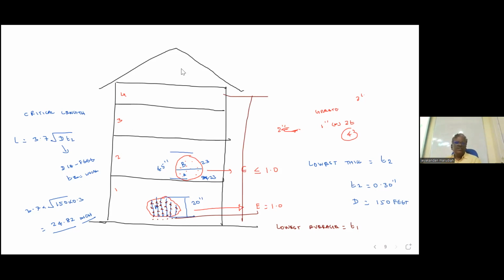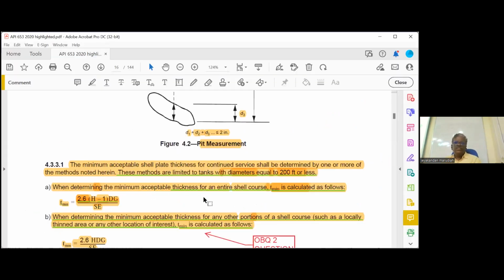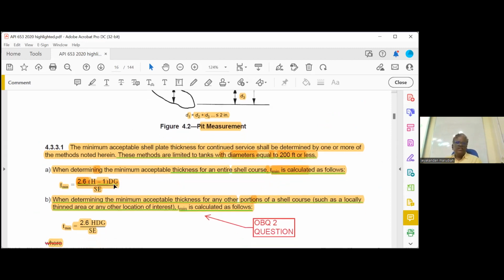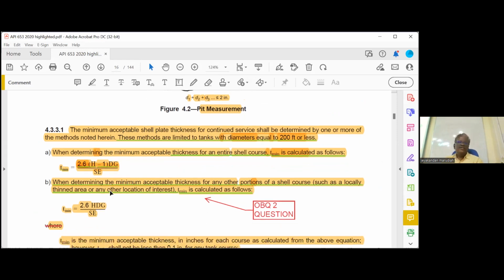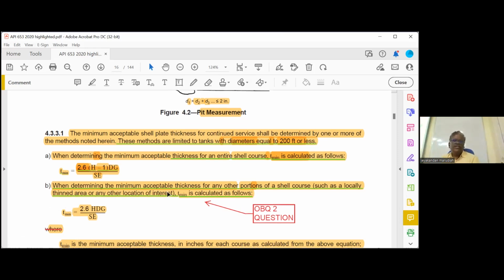So you can see 2 formulas. For determining the minimum acceptable thickness of the entire shell course, T minimum is calculated as 2.6 (H minus 1) D G divided by SE. If they are asking about the entire shell course, what is the minimum thickness? H minus 1. Only for a locally corroded area, H we have to use. When determining the minimum acceptable thickness for any other portion of the shell course, such as locally thinned areas, it is 2.6 H D G over SE. Now, you know H. What is H? Design liquid level from the corroded area. But for the entire shell course, we will take that joint.